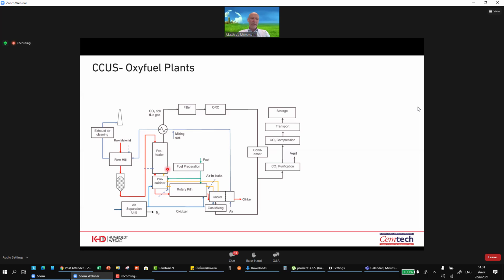You see the preheater and the precalciner, the rotary kiln and the cooler as the core of the clinker production process. And what's different from a regular process is that you take the off gas of the preheater, well, you do some energy recovery, but in the end you recycle it and bring it back into the cooler and add some oxygen to it. So you run this process with the recirculated CO2-rich gas, which you enrich with oxygen, just so much that you can burn your fuels. And then you can constantly branch off highly CO2 concentrated off gas and lead it towards purification and compression, and then transport and storage or utilization as you like it.